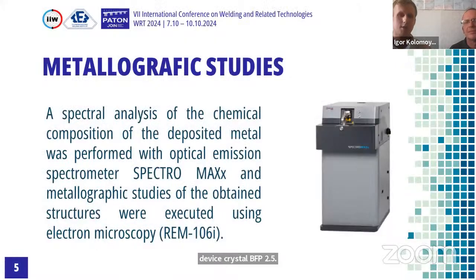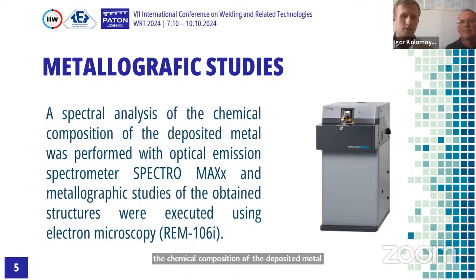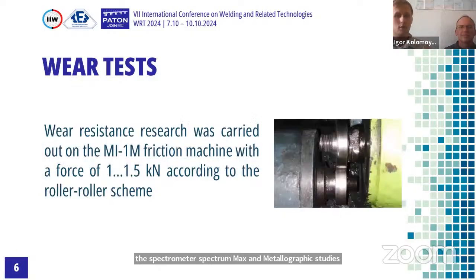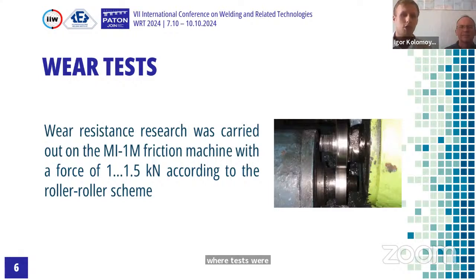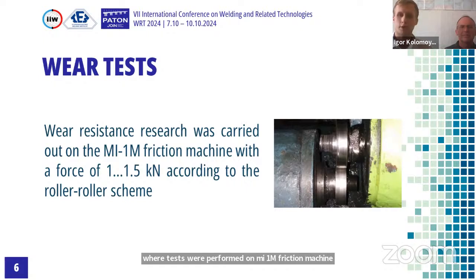Metallographic studies included a spectral analysis of the chemical composition of the deposited metal. It was performed on a Spectrum Max spectrometer, and metallographic studies were obtained with electron microscopy. Wear tests were performed on an MI-1M friction machine with a force of 1.5 kilonewtons according to the roller scheme.